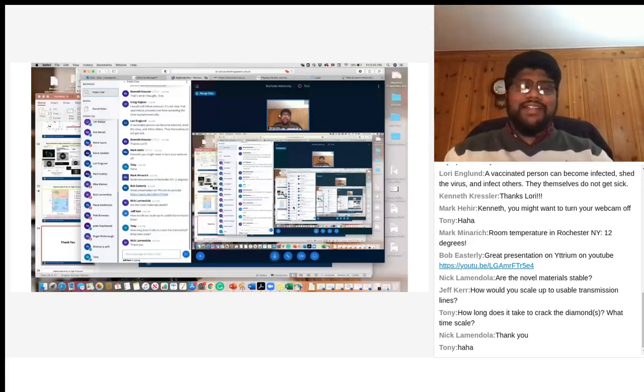Tony asked, how long does it take to crack the diamonds? What time scale? Oh, well, it depends on your luck. It can happen in any minute, or you will have months or years in the same high pressures. Sometimes you will see there's a huge noise when a diamond breaks. You will hear it, and you're like, here goes $4,000. Right. It can be seconds. It can be months and weeks and years. It depends on the experiment.